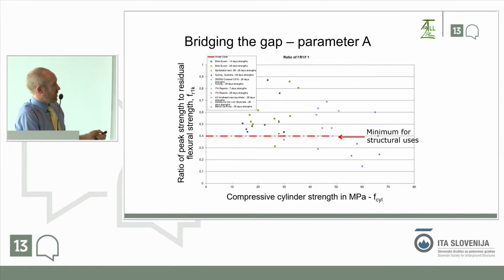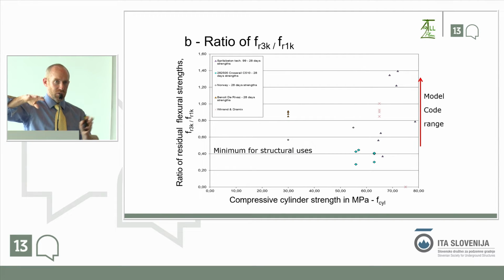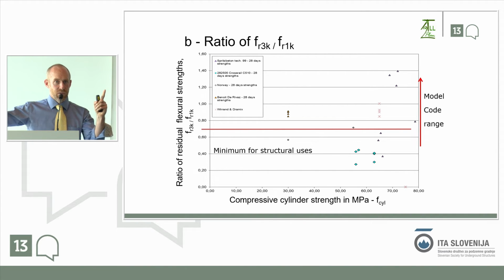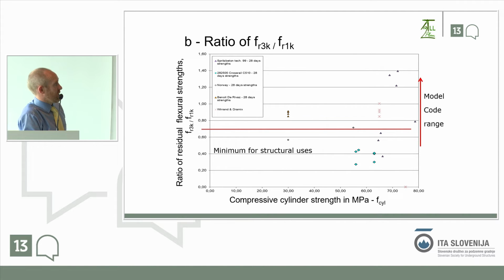And again, putting this data together, you can see that it's quite reasonable to assume that the first residual strength, FR1K, is about half of the peak strength, which is based on the tensile strength of the concrete itself. And then if you look at that slope, basically, and this is the way the specification is set out in the model code, they have different classifications, A, B, C, D, E. And basically, if the strength towards the end of your beam test, the FR3K value, is between 0.7 and 0.9 of the first residual strength, then that's a class B. And you can see there's limited data here, but that's a reasonable assumption to make. These are numbers that are achievable by the contractors with typical mixes. So again, I'm plotting obviously a variation with the strength there.